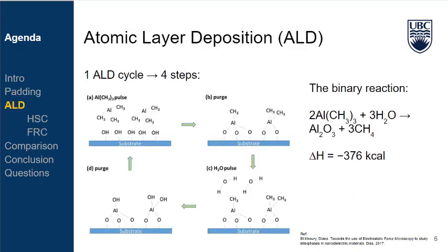Atomic layer deposition is a thin film deposition technique based on layer by layer chemical deposition. It is a subclass of chemical vapor deposition. However, ALD can achieve more delicate deposition at a nanoscale of less than 10 nanometers, the thickness of a layer of aluminum oxide. Most ALD processes contain two time-separated half reactions.